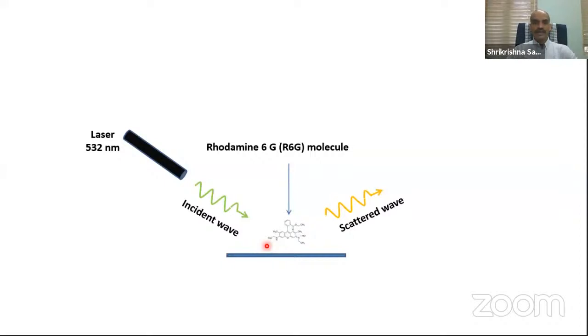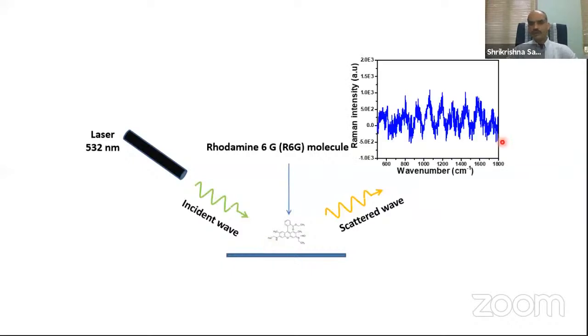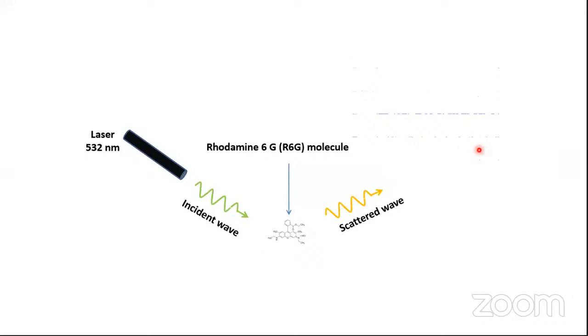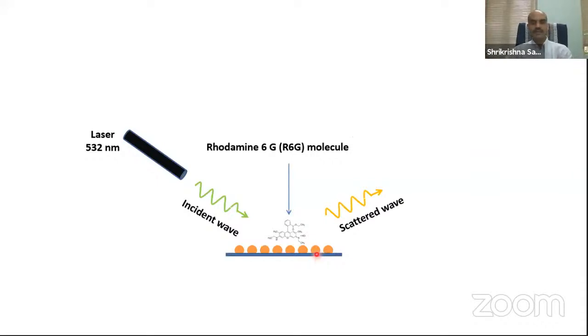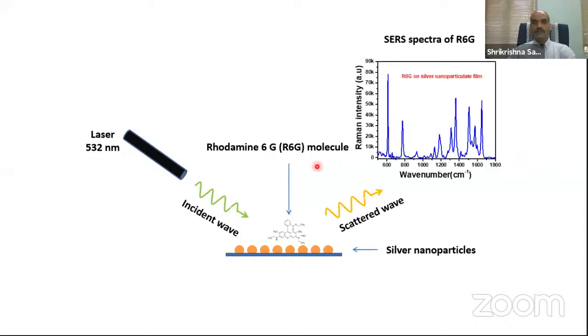If I have only rhodamine 6G, you can see that the intensity is almost zero. It's a very noisy spectrum, so you cannot say anything about whether there is any R6G molecule or not, because all this is noise. But if you put this rhodamine 6G on, let's say, silver nanoparticles or gold nanoparticles, where the surface plasmon resonance occurs close to the incident wavelength, what will happen? The Raman signal, earlier we had zero intensity, now becomes almost 80,000. So from 0 you can get 80,000 intensity.